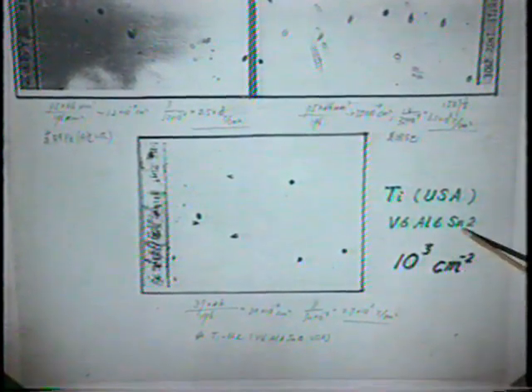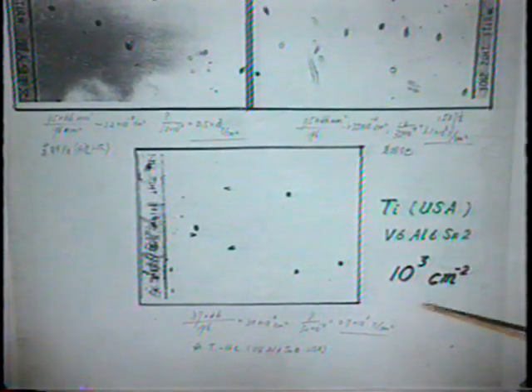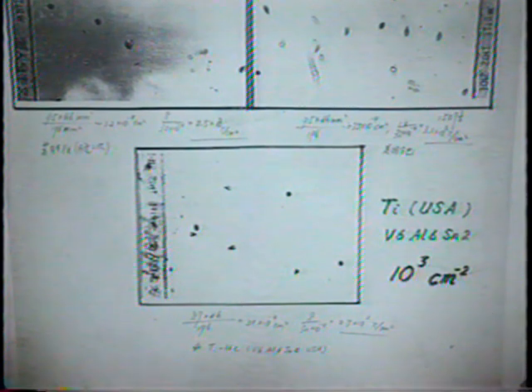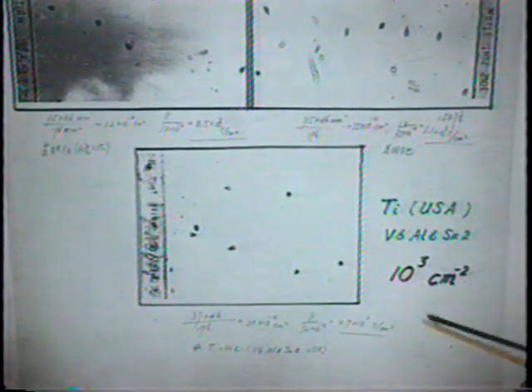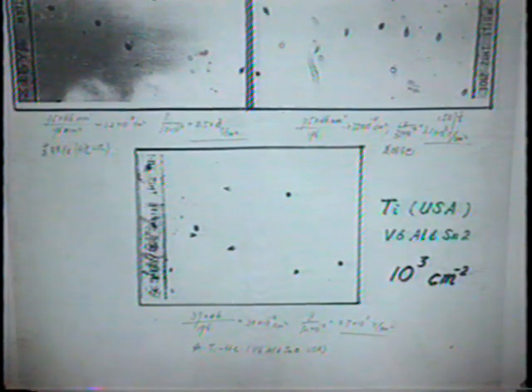Then we started to use titanium, an alloy with vanadium, aluminum, and tin. The density is almost the same, about 10 to the 3rd per square centimeter. The background usually is less than 100 per square centimeter, even 10 per square centimeter. We monitor this every time.